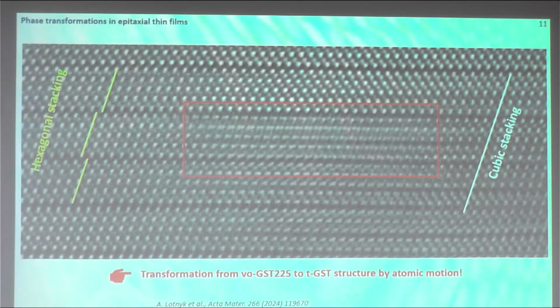And here we also looked at the mechanism of this transformation. We found some interesting areas here. So one part of our grain is hexagonally stacked, so this is the trigonal phase. Here's a cubic vacancy ordered phase. Here's also vacancy ordered phase. And in between we see some contrast. So we see how the lattice shifts against each other, and how the atoms, like here, have doubling of these atomic columns, and it suggests that the transformation occurred by small atomic motions in this direction. So the system shifts one against the other.